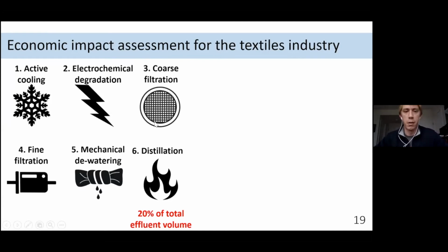And this all boils down to the final stage, which is distillation, which today actually accounts for about 20% of the total effluent volume being treated in that manner, mostly based on the inability of those coarse and fine polymeric membranes to really handle higher concentrated effluent sludge, which is created when you pull out more water from that mixture through the membranes.